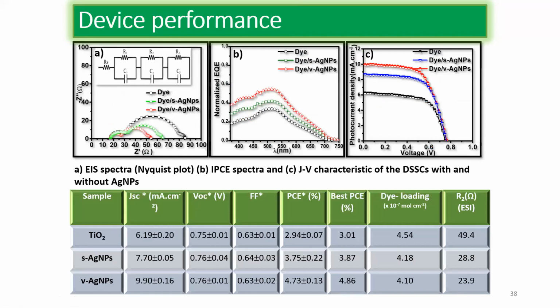After this, I fabricated the device, and these are the device characteristics. We see that the efficiency of the device improved from 3 to 4.86, which is almost a 50% enhancement in efficiency. The same can be observed in the IPCE, which is the EQE spectra, showing how many electrons are generated for the photons given to the cell. This gives an overall idea, and we see that the spectral response is really very good when I apply the plasmonic nanoparticles.